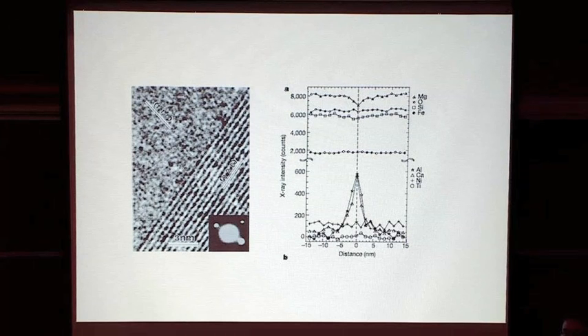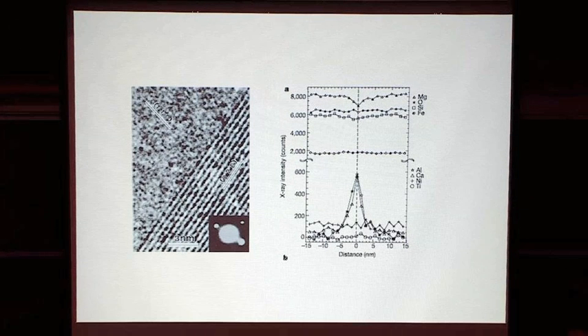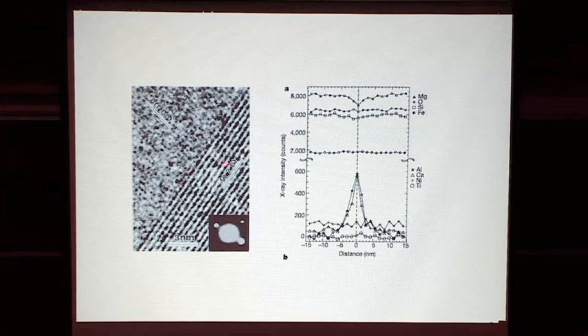Colin? If you wet the grain boundary, would this effect go away? If you wet the grain boundaries. Yeah, if you're undergoing partial melting, would this grain boundary actually partition between a solid and liquid? Yeah, we should be careful. I didn't include a lot about melt textures, and in fact, I didn't include anything about melt textures. But in general, small amounts of melt aren't on grain boundaries. They're in three-phase junctions, right? They're in the triple junctions.